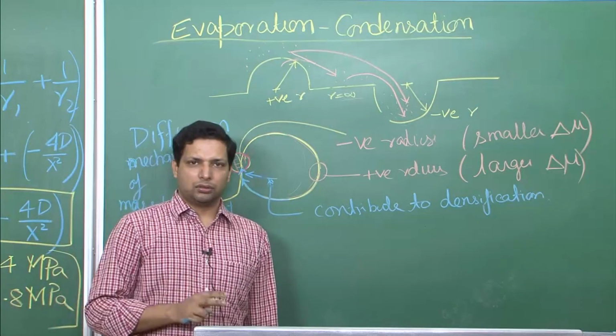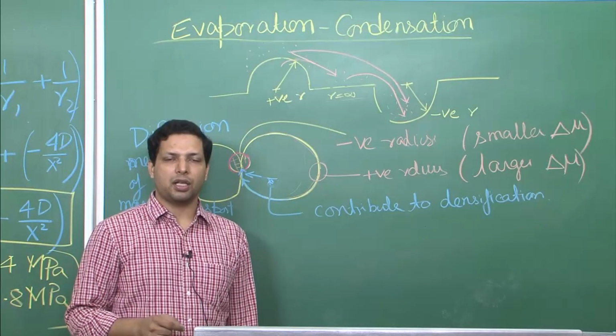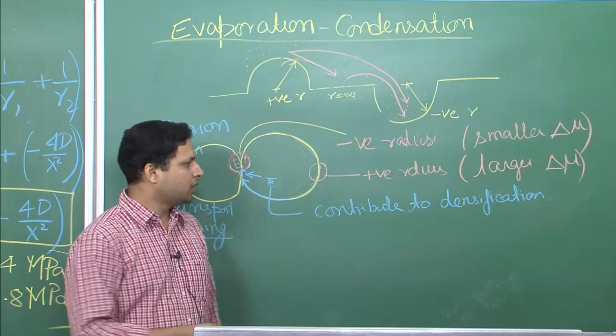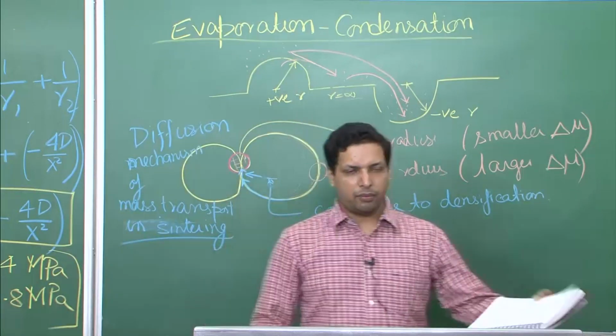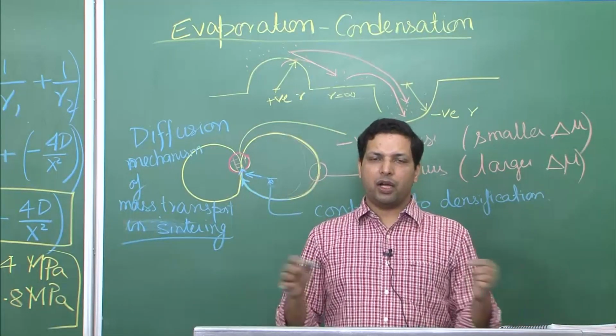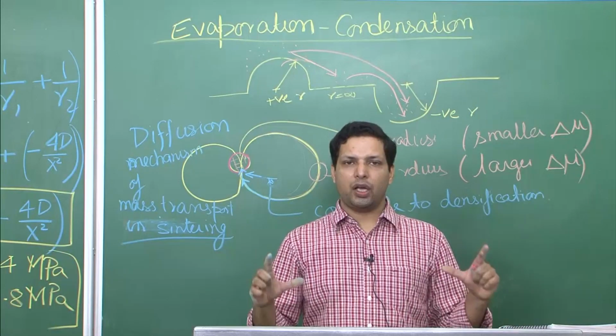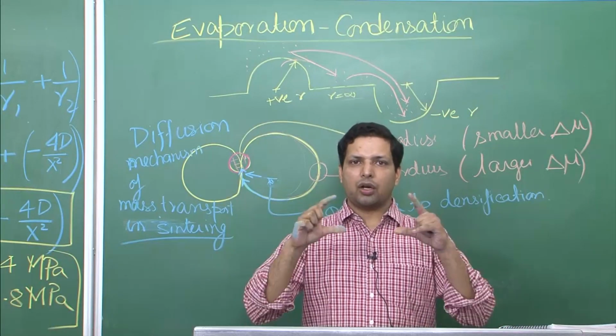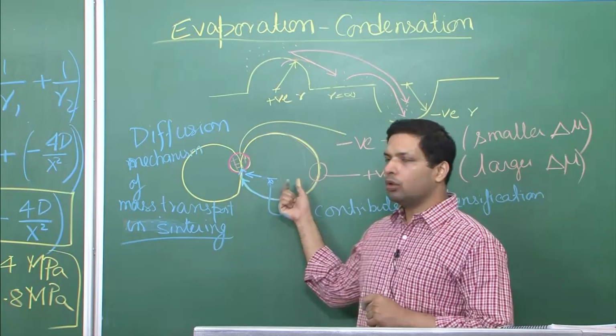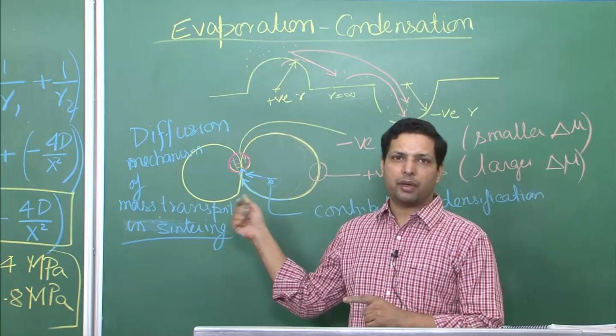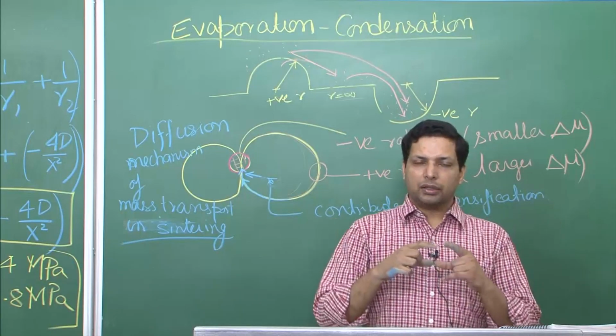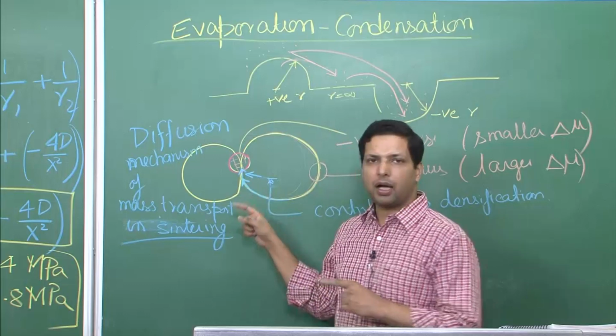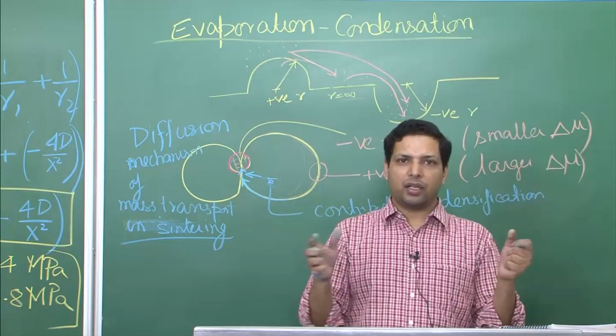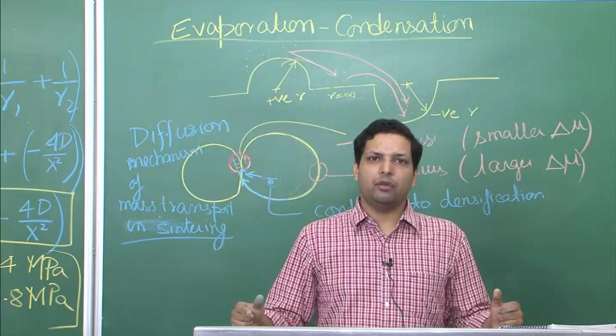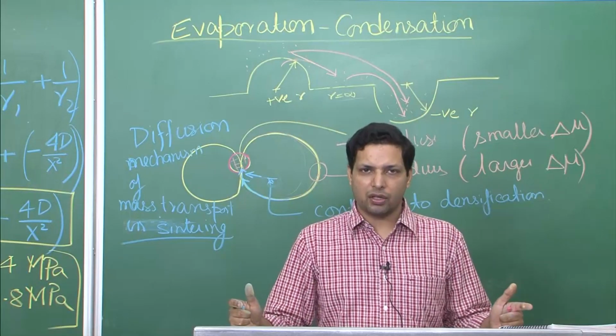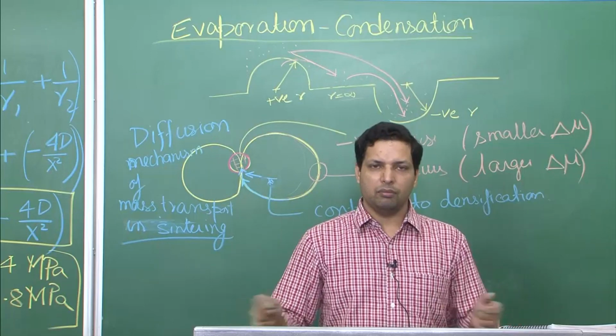So, we should not confuse that whenever sintering is taking place, densification will also take place. Densification and sintering may be independent. However, when we are looking at a much larger picture where you have a whole lot of particles, then no matter what kind of diffusion or mechanism is taking place, just because some pore regions in between are disappearing, the material will have the tendency to shrink, and so overall you will always get some amount of densification no matter what is the mode or mechanism of sintering.